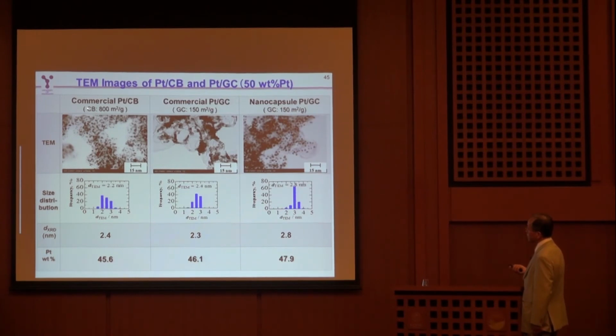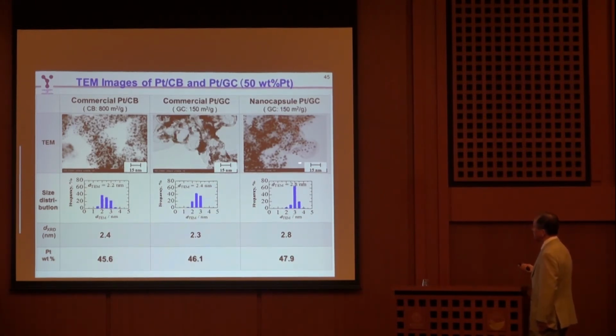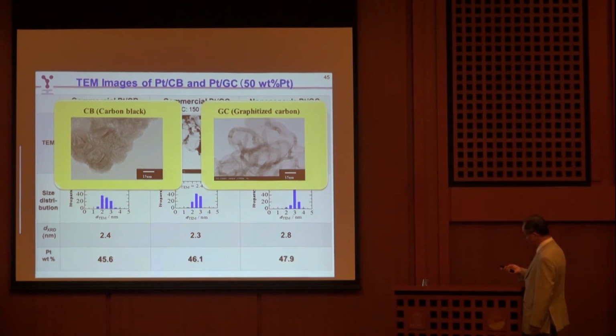The commercial carbon black support has a very high surface area, so the platinum dispersion is easy and forms a very nice distribution. But the low surface area carbon support, even the commercial one, does not give a good distribution of the catalyst. Only the step sites or such places show more catalyst. But by our method, even using the same carbon support, we can get a very nice particle distribution on the surface, comparable to the commercial high surface area carbon, and the particle sizes are almost the same. Such a carbon support has a different crystal structure, so this is more stable.